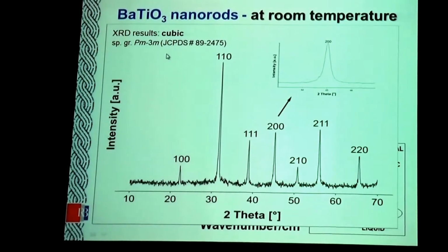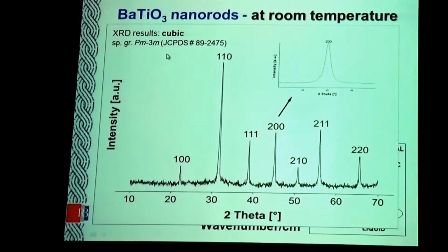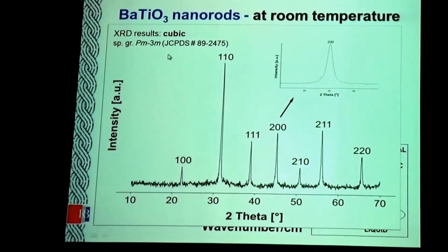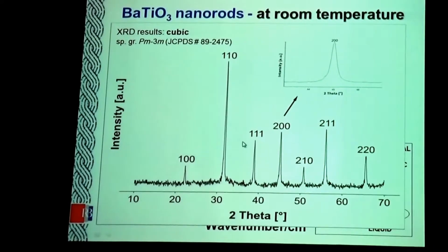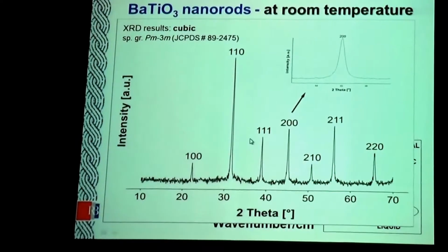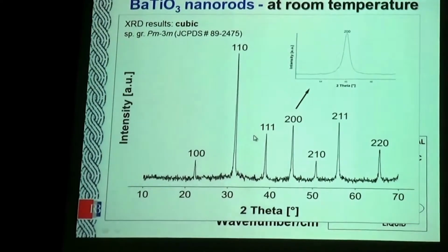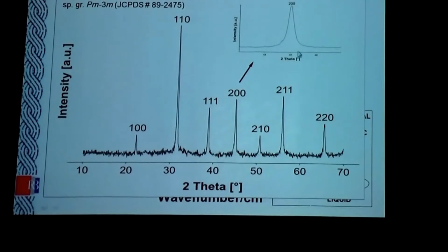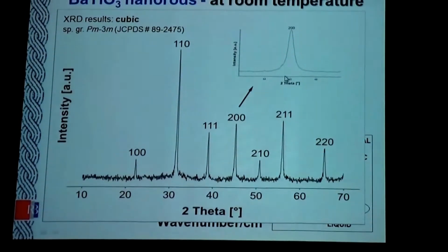There is a very small amount of hexagonal structure which cannot be observed by X-ray diffraction, and as I already mentioned, tetragonality in barium titanate is very small. The ratio between the C and A axis is just very small, so it cannot be resolved with X-ray diffraction. This is an example of one of the lines.